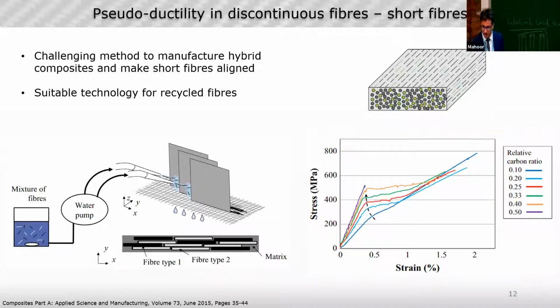There is a method coming from a research program, HyFiSyn, and they invented this technology where short fibers are mixed in a water solution. They are put on a kind of grid, and they are dried. Using vertical plates and some vibrations, the short fibers are aligned with each other. And this is very good also for using recycled fibers. There are research papers that show that this pseudo-ductility was achieved even employing recycled fibers in the layup, which is very good considering the issues we have in recycling composite materials.